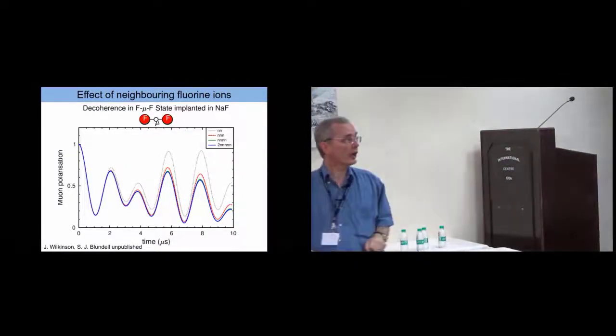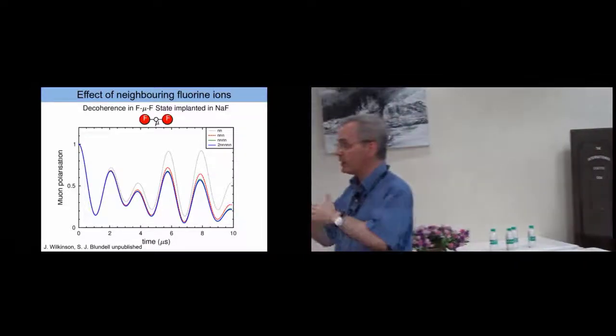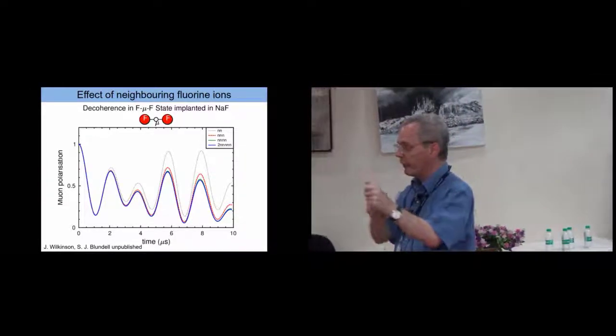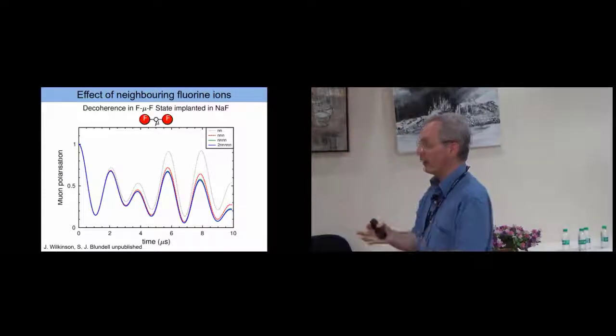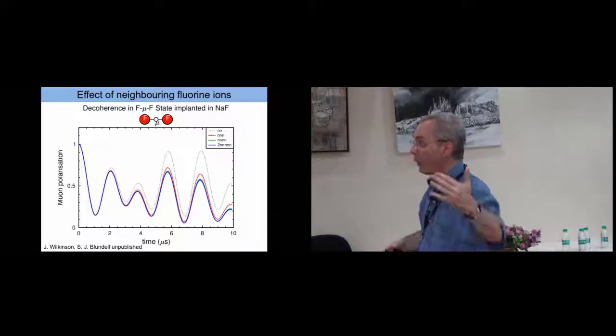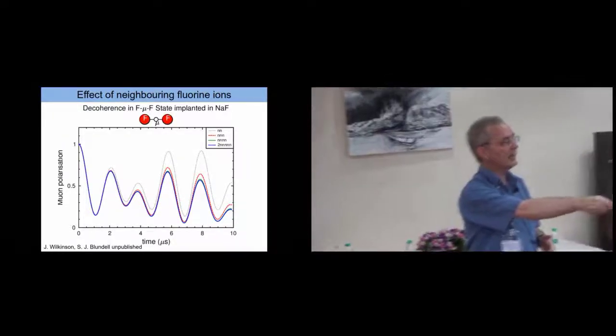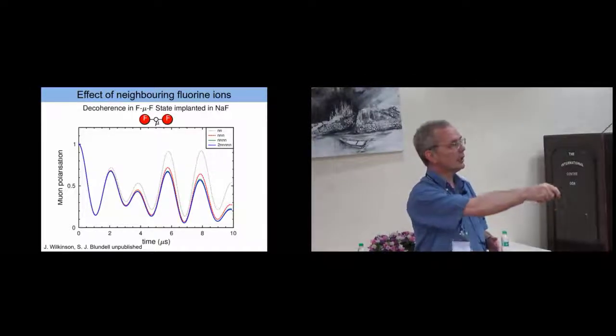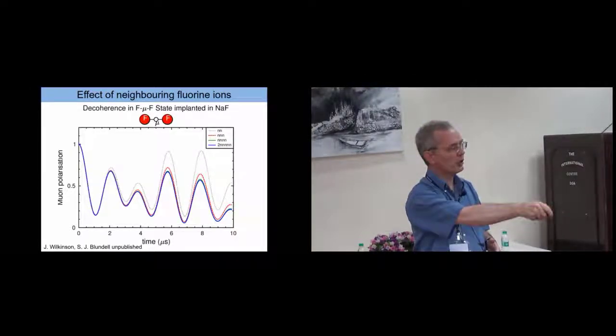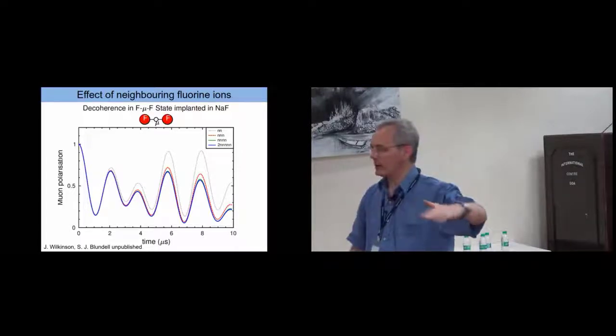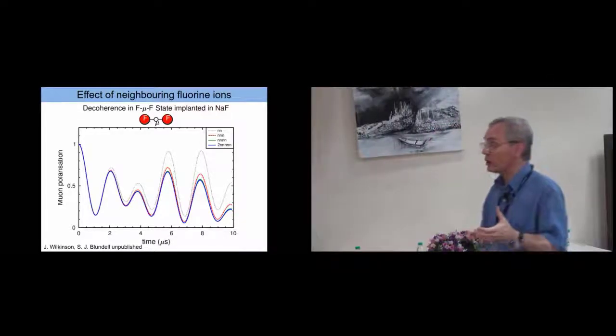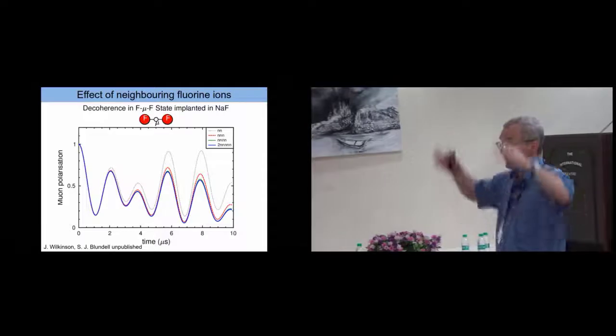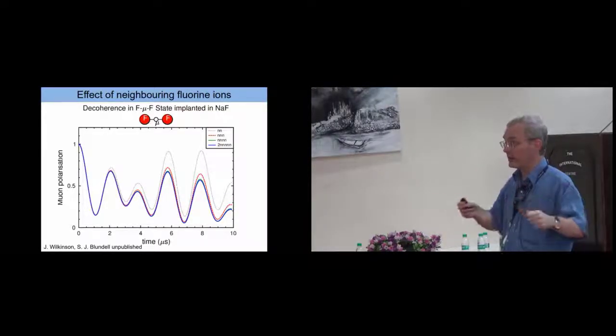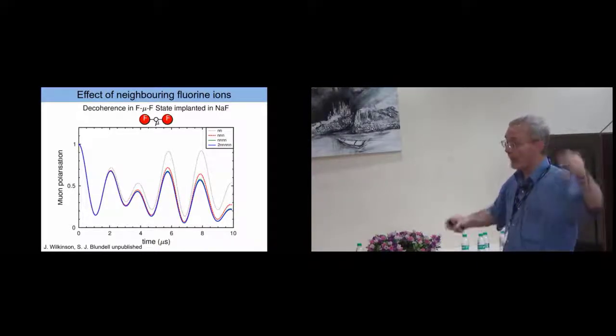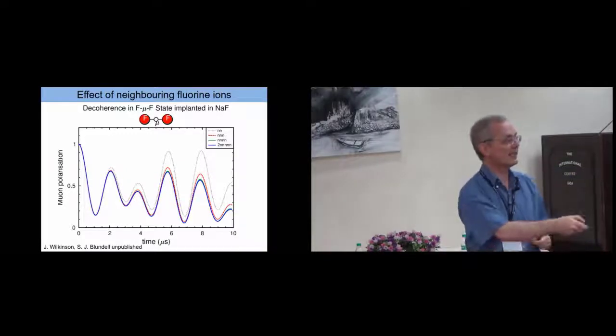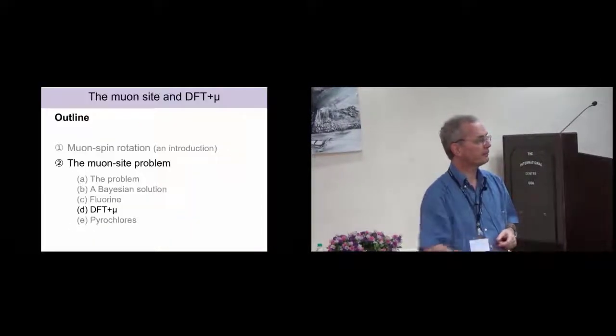In fact, something we've been working on very recently is, as well as thinking about the fluorine-muon-fluorine, to think about the neighboring fluorines as well. They're further away, and what they tend to do is lead to decoherence. So you get a relaxation of these oscillations, which up until now we've always fitted using an exponential. But in fact, you can do it by considering, you need large matrices to do this, but you can consider coherently all of the next nearest neighbor and next-next nearest neighbor interactions.